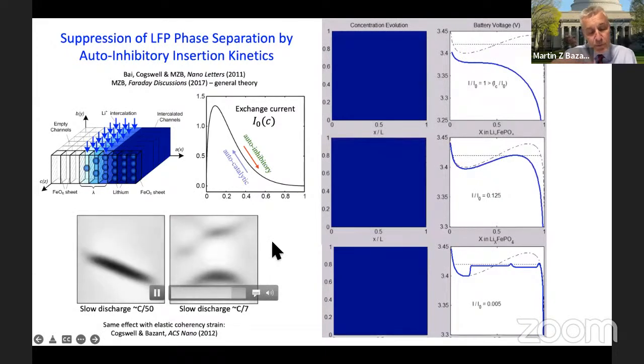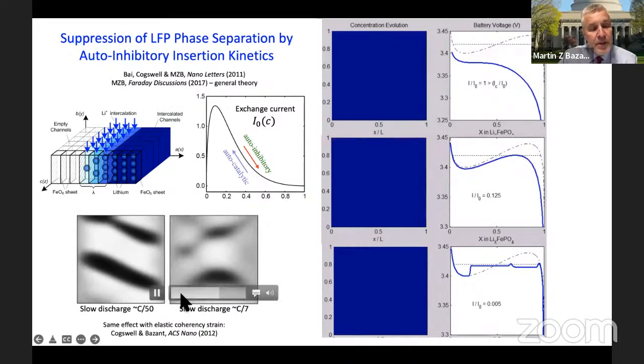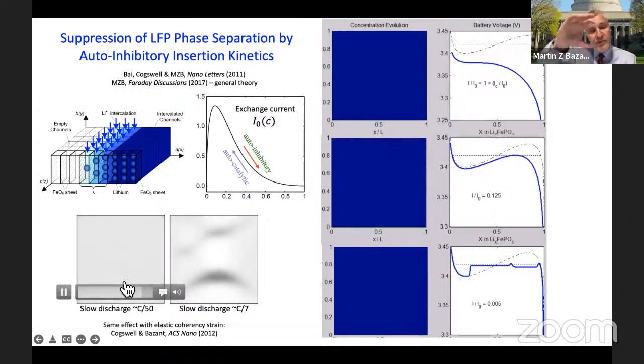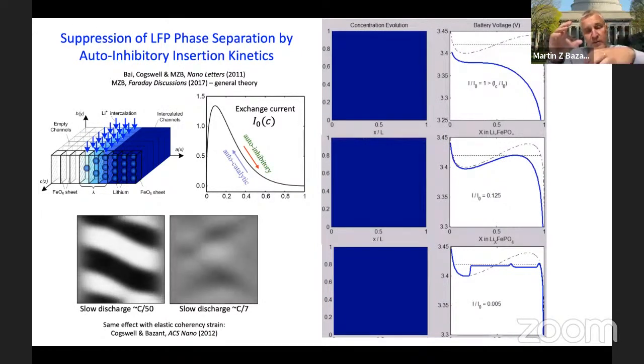Now, I believe that the suppression of phase separation is one of the reasons that lithium iron phosphate is an excellent high rate material, because these phase separations are kind of erased at high speeds. But at low speeds, you do get the phase separation, and this tilting you're seeing and these interesting patterns come from coherency strain. So basically fitting together the different pieces of the lattice to minimize the strain energy.